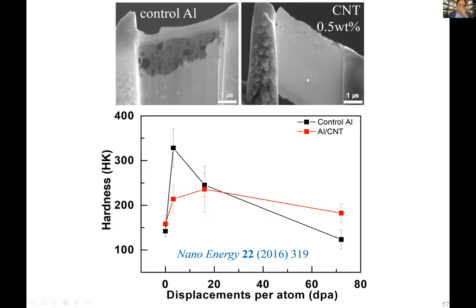And when we do the hardness measurement, so this is a mechanical measurement, we see that when we have the control aluminum, without the radiation, our aluminum is a bit stronger with carbon nanotube, but with radiation, it very strongly hardens. This is actually not a good thing. Within just a few dpa, it reaches a peak hardness because of radiation defects. And then it sort of seems to soften. Now this softening is not because the radiation defects are gone, it's because it starts to swell and sort of turn into this Swiss cheese morphology.